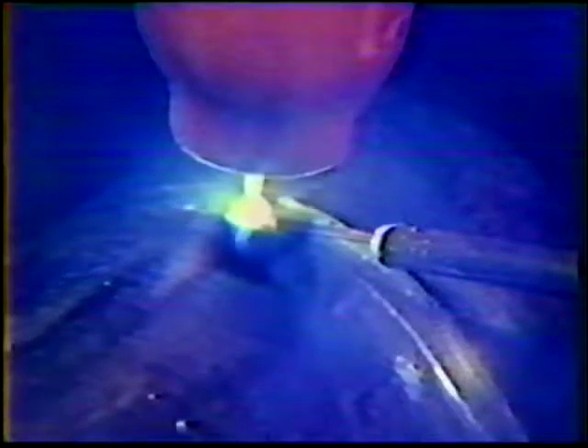The wire feed is usually stopped during the downslope portion of the weld cycle. The major consideration here is to prevent the addition of filler metal to a cold puddle. The wire feed may be continuous, similar to a manual lay wire technique, or intermittent, similar to a dip technique. The intermittent technique is normally used with pulsed current to apply filler metal during the high or the low pulse.